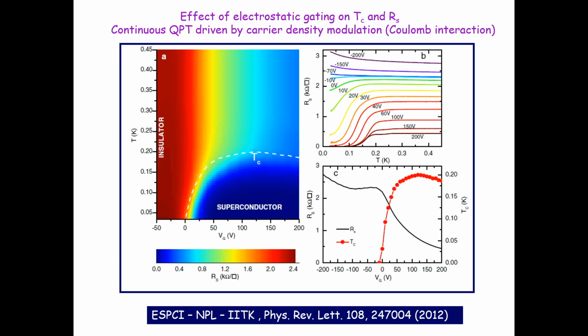So all the information that I have from these two insets can be drawn in this colorful picture, where you have the gate voltage, you have the temperature, and the color code tells you the sheet resistance. When the sheet resistance is very, very small, you have superconductivity and metal here. When the sheet resistance is up to around 2.5 kilo ohm per square and beyond, it's not actually an insulator, it's like a dirty metal over here. So the question was, why this kind of dependence on gate voltage? Why is the sheet resistance not linear, for example, as a function of gate voltage?